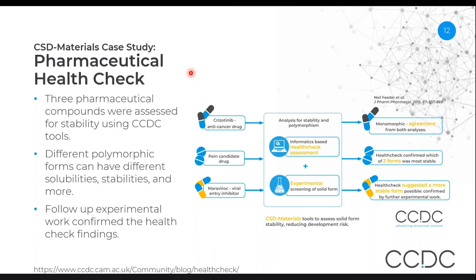The reason why that is important is because different polymorphs can have different solubilities and stabilities. So if a molecule undergoes a phase transition into a different polymorph, your drug tablets can potentially collapse or be less bioavailable than you might expect. Follow-up experimental work was done based on our recommendations in order to confirm the findings as well.